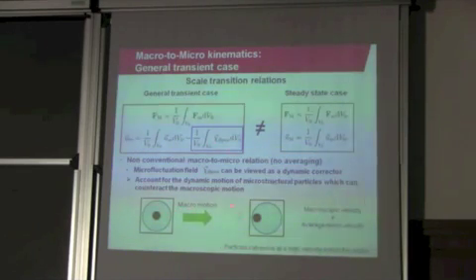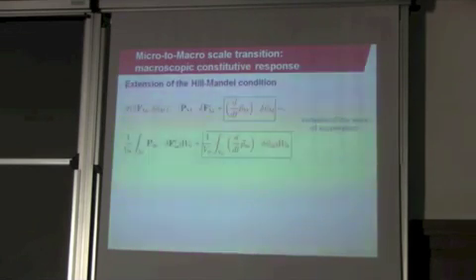And that's also an illustration of how to understand this scale transition relation. If you have the macroscopic motion, so that the whole unit cell moves with a certain displacement, the microstructural locally resonating particle does not necessarily move with the same displacement, but, as a matter of fact, moves even in the opposite direction. And that's a graphic illustration of this relation.